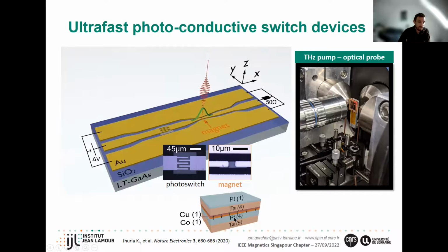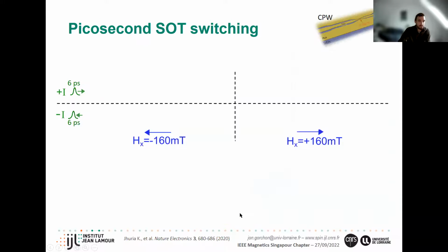The goal is to have the spin Hall effect in the platinum and the tantalum, and to inject the spin currents into the cobalt and torque it. So we first did the experiments with long pulses, microsecond, millisecond pulses, and confirmed that we had spin orbit torque switching. And then we went to our platform where we could generate these short 6 picosecond current pulses.